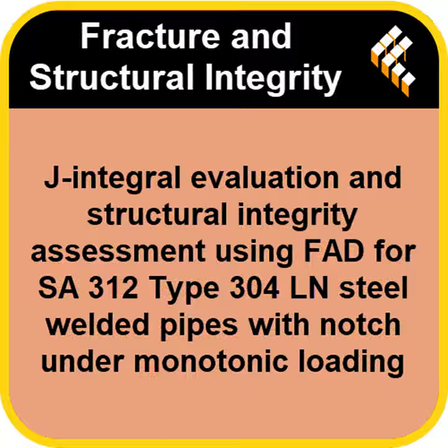Exactly. The study we're looking at focused on real-world welded pipe specimens. They used 3 specific pipes of that high-toughness SA312 Type 304 LN steel. And crucially, each one had a large, manufactured, circumferential through-wall notch, a simulated, pretty serious crack placed right in the weld zone. Right. They weren't testing pristine, perfect pipe. They were deliberately testing damaged pipe to see where the limits really were.